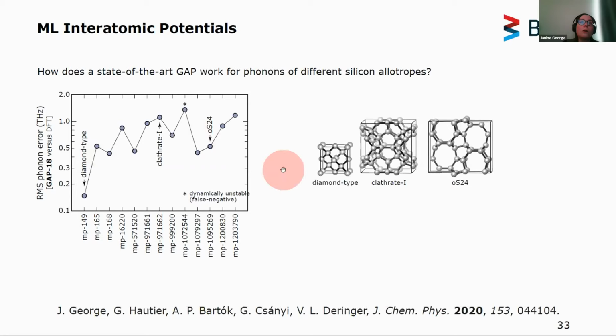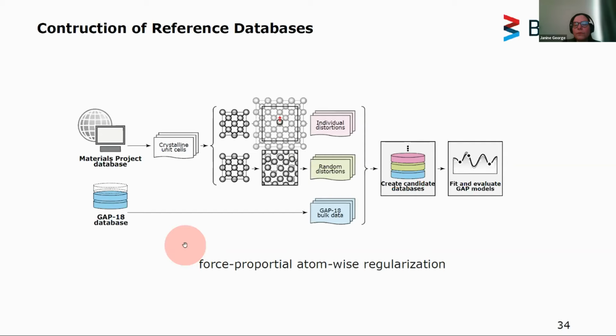But we were able to arrive at a good GAP model when we were constructing new reference databases. So we took data from the Materials Project database on crystalline materials, built supercells with individual and random distortions, and included this in this initial GAP18 database. And then fitted and evaluated all these kind of models.